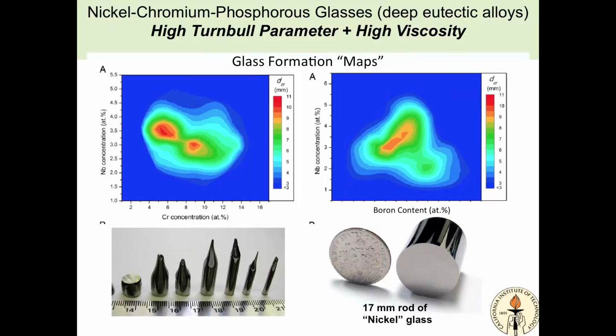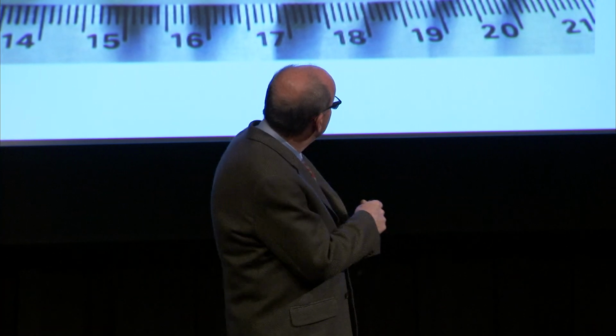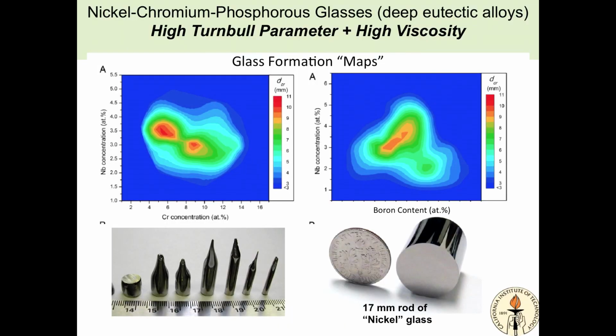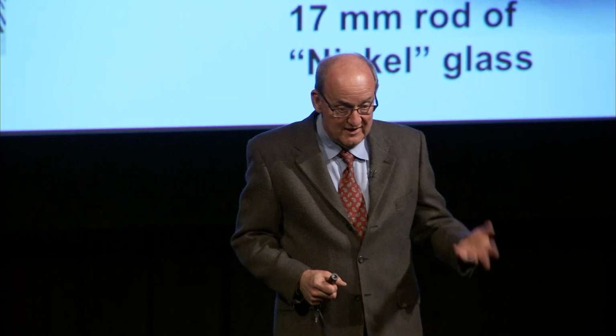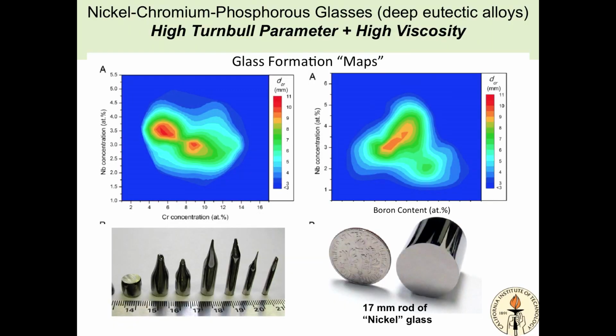So we play games. These are maps. And we were interested in developing practical metallic glasses that you can use. This is recent work, now we're up to 2008, 2009. So we were exploring iron, nickel, chromium metallic glasses. We alloyed them with things that have deep eutectics, like phosphorus and silicon, and we coax it into a very deep eutectic and squeeze out the crystallization, and we make bulk glass. Except these glasses are chromium, iron, nickel. What's that? Called stainless steel.